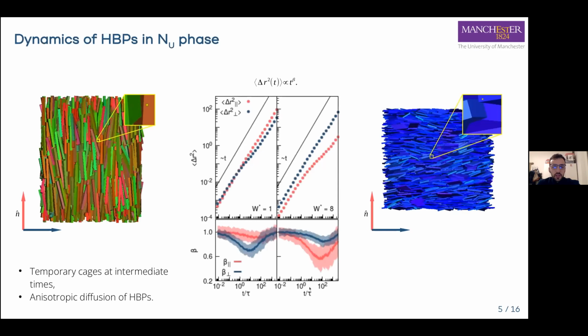So we investigated the diffusion of, first of all, the hard board-like particles in uniaxial nematic phases. These particles interact only with hardcore interaction, and from their phase behavior, we know already that at certain packing fractions, due solely to their excluded volume interactions, they can reorient and reorganize and form nematic phases. These can be prolate nematic phases for prolate particles, as you can see in the snapshot on the left, and oblate nematic phases for oblate particles, where the nematic director is orthogonal to the length and the width of the particle.